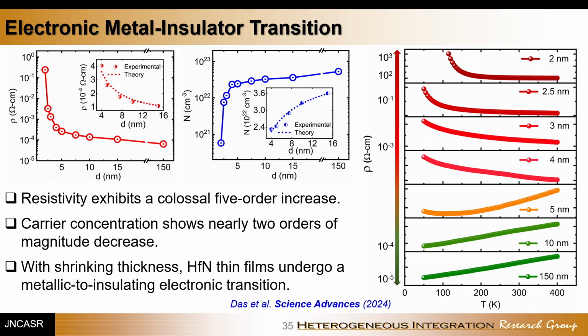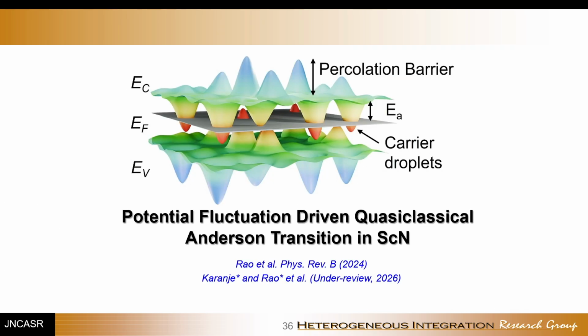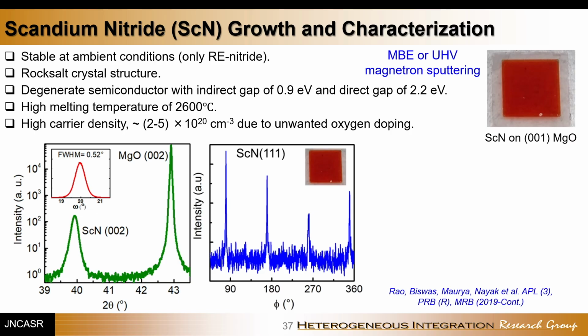In this case, of course, because of the strong confinement, because of the strong localization effect, plasmon resonance basically breaks down. So that was our second demonstration of metal insulator transition in a transition metal nitride. And let me now tell you the third example that is driven by potential fluctuation in another nitride semiconductor, which is scandium nitride. So before I go to the physics behind it, let me just tell about scandium nitride in one slide.